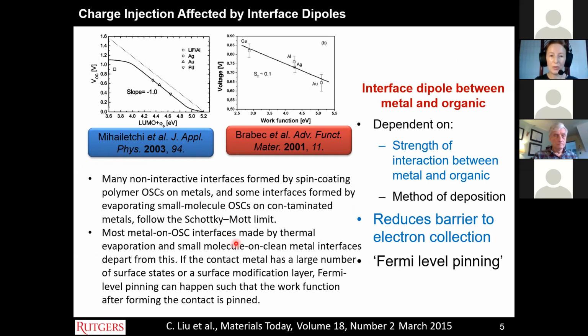Interestingly, if you thermally evaporate the metal onto a polymer, you'll create Fermi level pinning. And so you'll see a very weak dependence of the voltage on the work function of the metal. My point is that when we create devices using the inverted fabrication method, we will have a very high sensitivity to the work function of the electrode. Whereas in the conventional devices, when the metal is evaporated, you have very little sensitivity to the work function of the metal. So it becomes very important, when you're doing inverted fabrication, to be able to control the work function of the metal electrode.